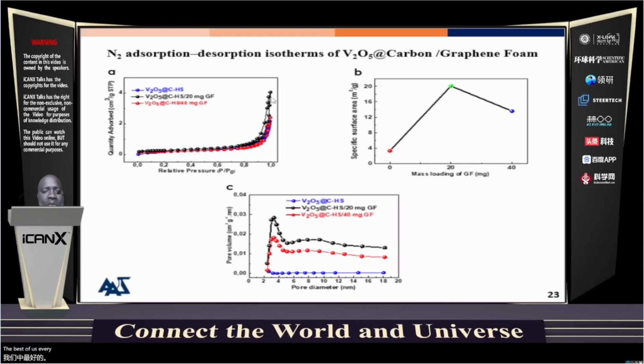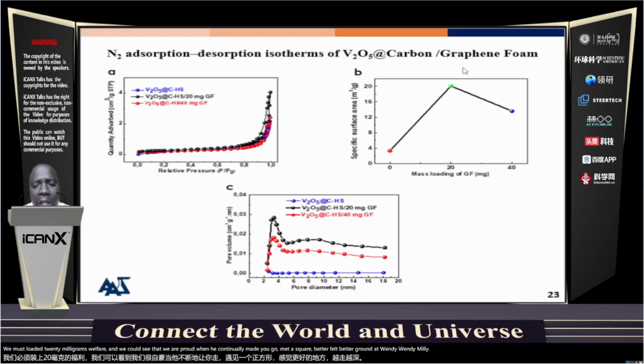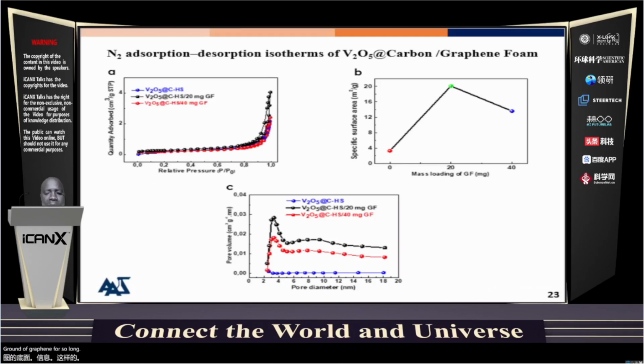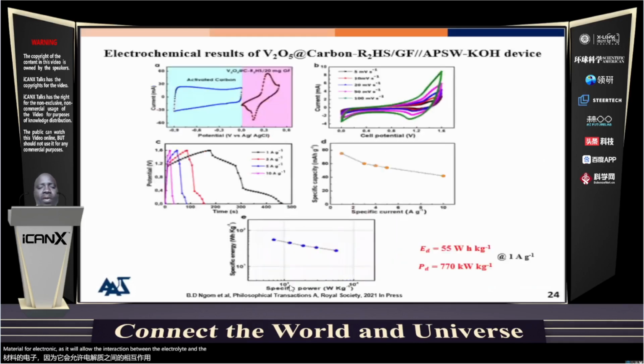The best surface area that we could find is when we imbibed, we mass loaded 20 milligram of graphene, and we could see that we are around 20 square meter per gram at 20 milligram of graphene form. So looking at the nature of the pore size and the volume of the pore, we could see that we are having a pore size comprised between 2 and 4 nanometer, which is a mesoporous material, which could be a best material for electrochemical. It will allow the interaction between the electrolyte and the active material.